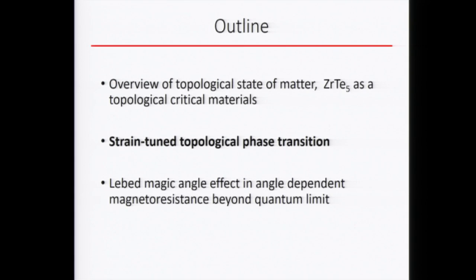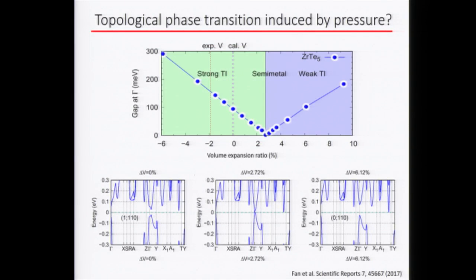Okay. So I'm going to tell you about how we use strain to go across that topological critical point. As I said, people immediately realized that the lattice constant is the key to changing the band structure of this material. There was a calculation based on this paper saying that you can tune from one phase to the other by isotropically changing the lattice constant.